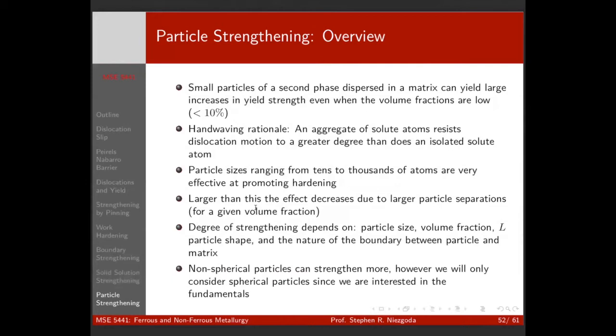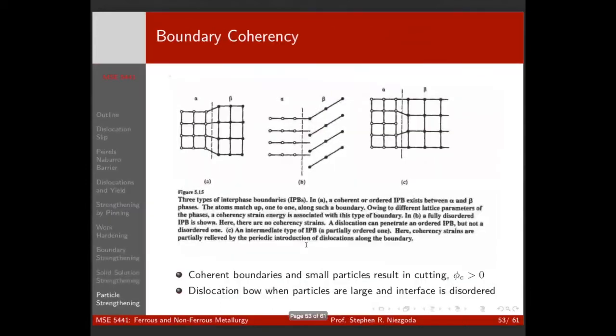So in terms of particles, we want particles that are hard to cut and hard to bow around, right? In an ideal world. So if we think about what that means for a given volume fraction, we want particles that are close together so we can't bow around them. And we want particles that are big enough that they're hard to cut through. All right? So what we want is a nice dispersion of fine particles. We'll talk about this a lot with aluminum.